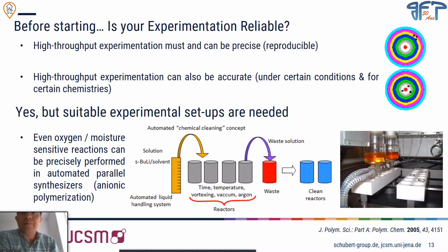and method development, basically experimental development, we figured out that the parallel reactors, the glass reactors you see in the picture, have different levels of contamination. So you have to clean them very homogeneously before starting any experimentation.